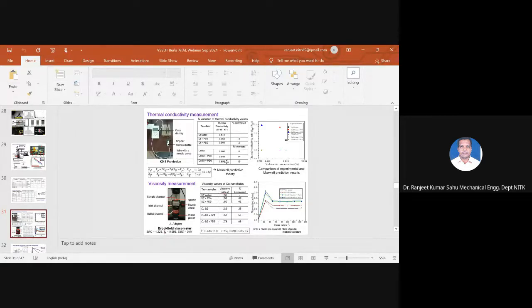And we have adopted the Maxwell predictive theory and compared it with the experimental value. After comparing, we are not getting a close agreement with the experimental value. So the Maxwell prediction is not good enough for our case, though we are getting spherical size particles. In the Maxwell prediction theory, we are neglecting some points which are not adaptable for this equation. Similarly, the viscosity of nanofluids we have measured using a Brookfield viscometer.